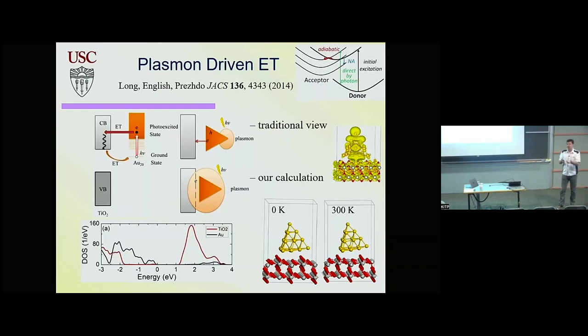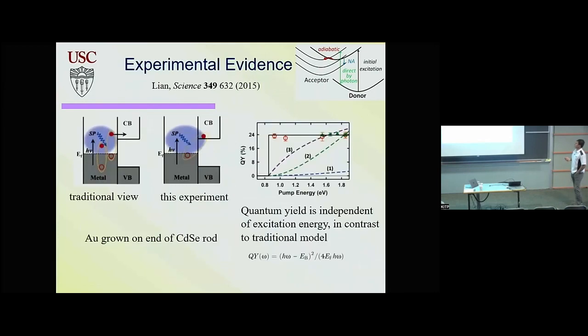But people see photovoltaic effect when you put a metallic particle on a semiconductor. And what we saw in this paper is that if you have special states, interfacial states, you have charge transfer excitation. So when you photoexcite your metallic particle at the plasmon resonance frequency, you have an excited state that leaks into the semiconductor. So you already have charge transfer during photoexcitation. So you have a charge transfer excited state. And so this was 2014, and 1 year later, Tim Lian actually showed this experimentally.